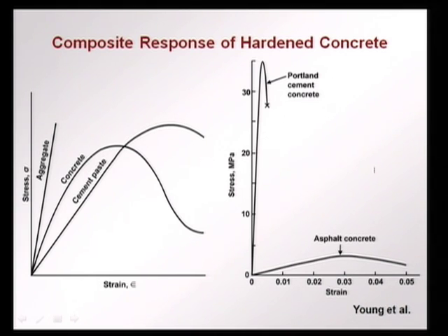If we compare the response of cement concrete or Portland cement concrete to asphalt concrete that we saw in the previous lecture, we have a similar response in the sense that there is an elastic part, there is a peak and then there is a drop. But if we put both these concretes on the same graph, we find that the strength of Portland cement concrete will be much higher than asphalt concrete. However, the strains that the material can undergo are much higher in asphalt concrete than Portland cement concrete. Portland cement concrete is much more brittle and much stronger than asphalt concrete. Otherwise, there is a lot of similarity in behavior.